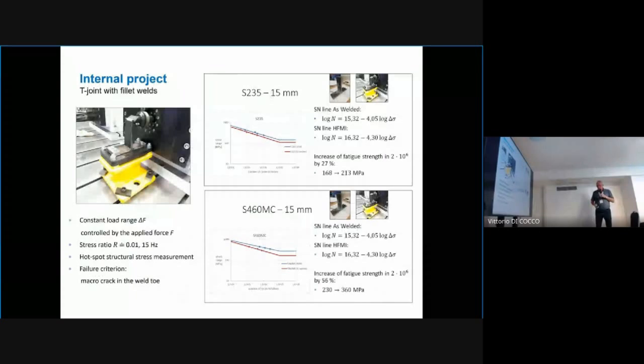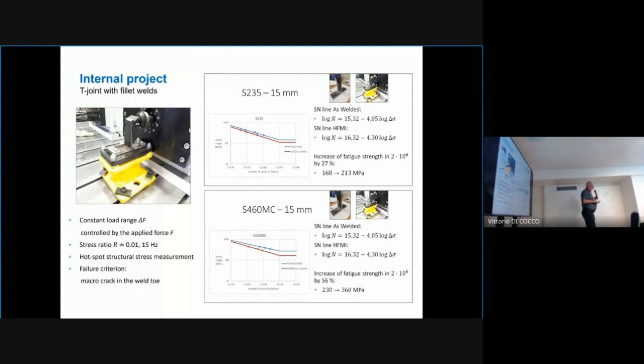We performed an internal project because an interesting thing is additional bending for the welds. We are happy to use this type of stand to investigate this joint with fillet welds, and again you can see only examples of the result. This is the application of HFMI for this type of steel, and you can see again that the improvement of the fatigue strength is better when we apply this technology to steel with higher yield strength.